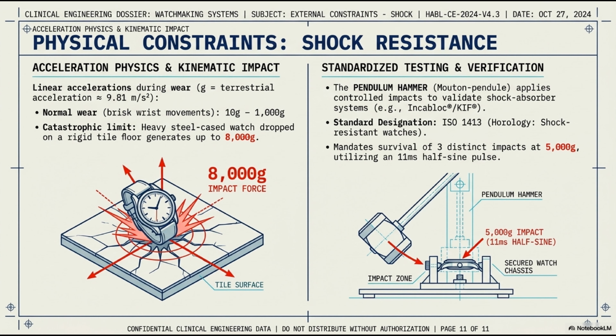Now we face the most violent physical constraint, shock resistance. Let's look at the kinematics of impact. Look at the diagram on the left. Normal brisk wrist movements generate linear accelerations between 10 g and 1000 g. But what happens if you drop a heavy, solid steel watch onto a rigid tile floor? The deceleration is instantaneous. That catastrophic impact generates a localized shockwave of up to 8000 g. Without protection, the brittle jewel bearings holding the balance staff will instantly shatter like glass.